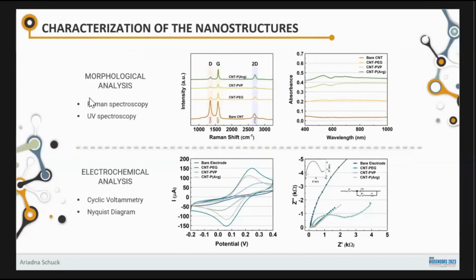So next part is the morphological analysis. First, I checked the Raman spectra to see if I can reduce the defects, as I can see in the same image. And based on the bands of the Raman spectra here, you can see that there is a reduction in the peak compared with the bare carbon nanotube, which means there is a reduction in the defects of that nanostructure. And next one was the UV-Vis measurement. The absorbance also increased when I use the carbon nanotube with polyarginine compared with the bare carbon nanotube here. This means there is a more uniform dispersion of the carbon nanotubes over the glass surface used for the UV-Vis.